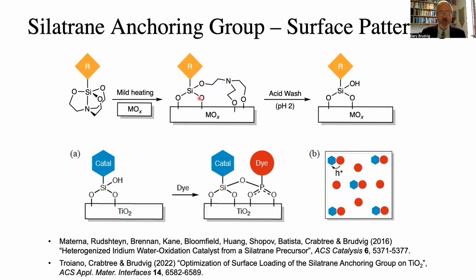One thing we've realized recently is that the protecting group, this triethanolamine protecting group, remains attached to the surface when we carry out this mild heating step. But we can remove it by an acid wash. And what this does is it exposes another binding site exactly adjacent to the first molecule that allows us to pattern the surface where we can put down a catalyst, for example, with a siloxane anchor. And then we can put a dye right next to it with, for example, a phosphonic acid attachment. And this allows the photochemical process to be done much more efficiently, where the dye can inject an electron into the conduction band of the metal oxide and then very efficiently transport holes to the catalyst because of the adjacency. And this is something we're very much working on right now.